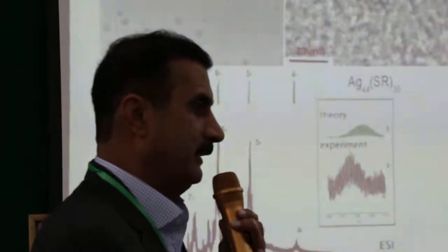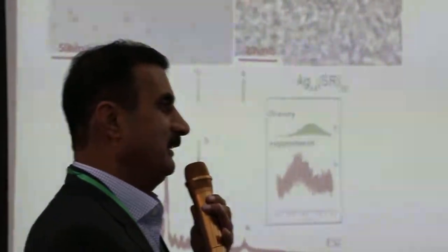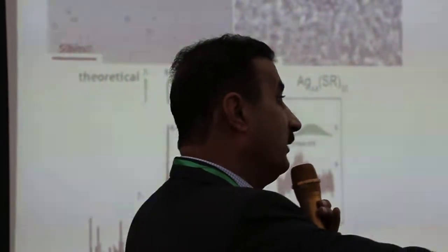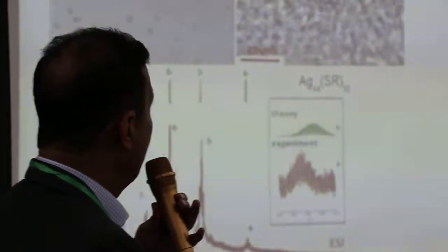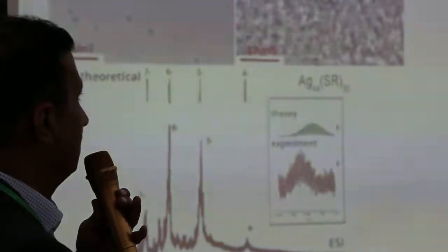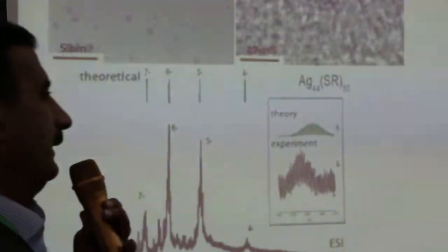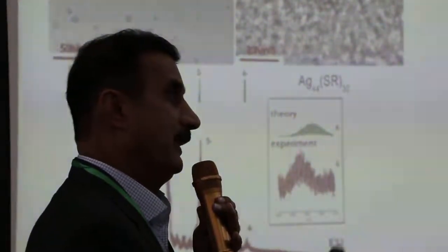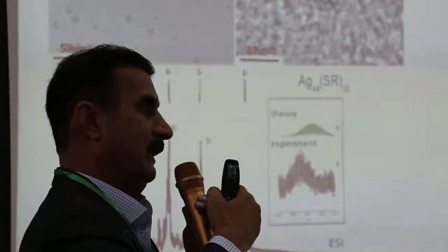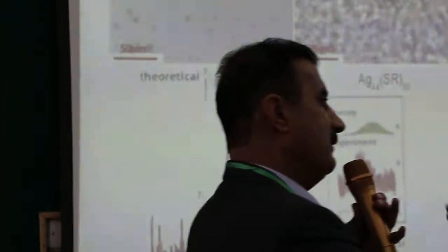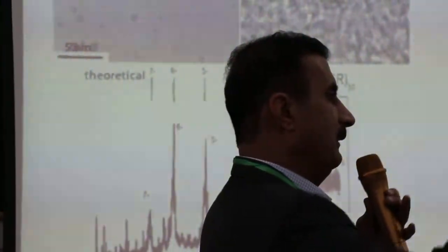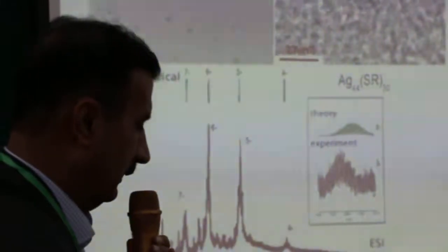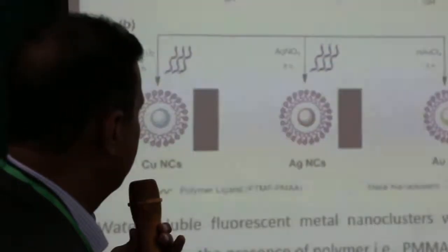The problem is these clusters are soluble in water, but for solar cell technology you need them soluble in certain solvents to make thin films. We are now designing new ligands which can make equally stable silver clusters that absorb a major portion of sunlight and act as a semiconductor to generate electrons. If we can make a very thin film of silver, it can hopefully be used for solar cells.